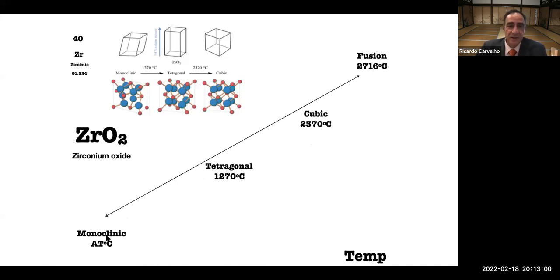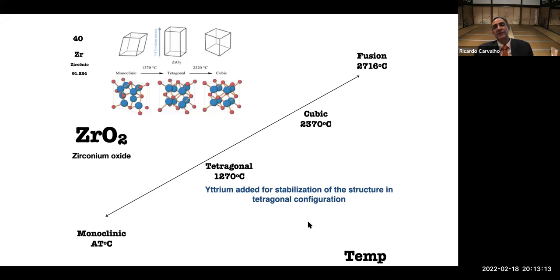If I bring zirconium oxide down to room temperature, it will always be in monoclinic, which is a very weak phase. I don't want that here. And that's what the manufacturers did in order to reach the tetragonal structure and then cool down to ambient temperature and still remain in the tetragonal configuration, which is the strongest. Yttrium was added exactly to stabilize the structure in this configuration.